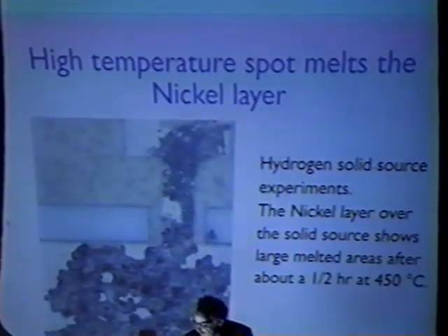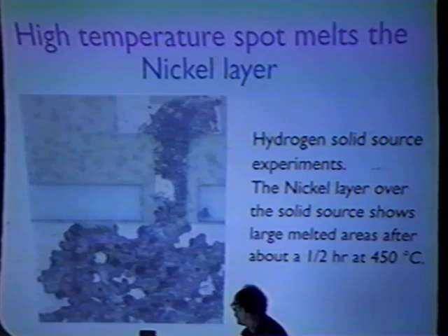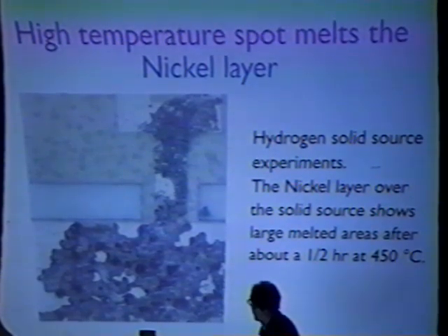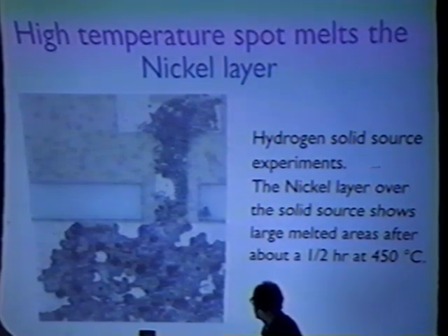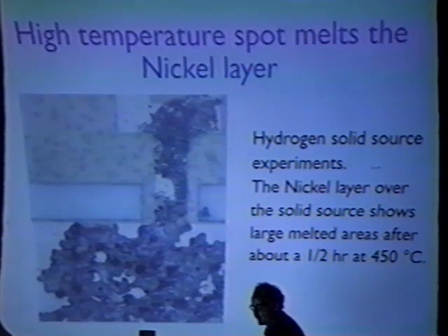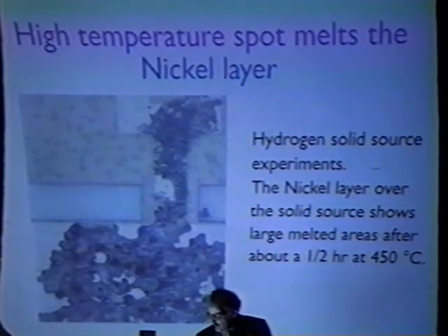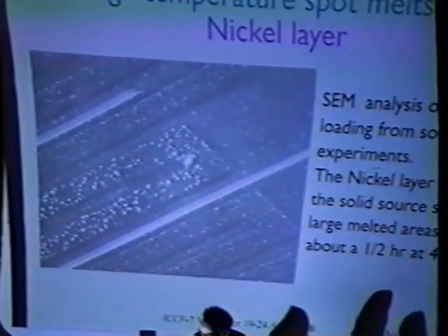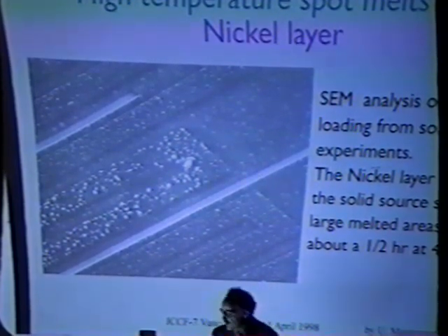After these cycles, looking at the cell, we can see many points, many hot spots where the nickel is melted. If you enlarge this picture, you can see many small drops of nickel layer. We have here an electronic microscope photo showing the destroyed part of the resistor.